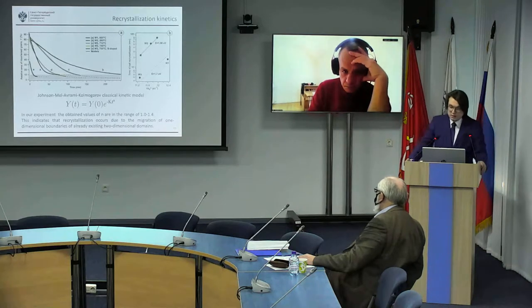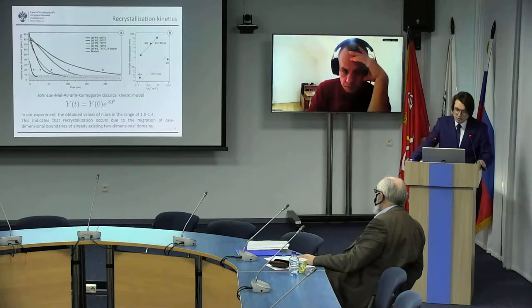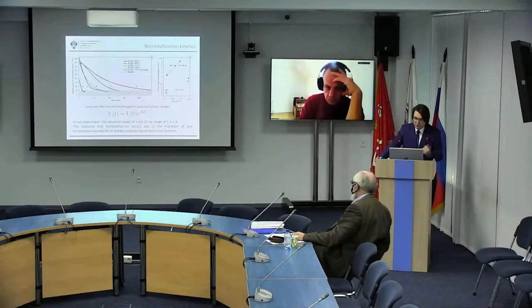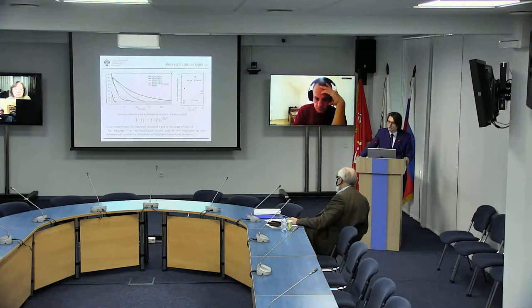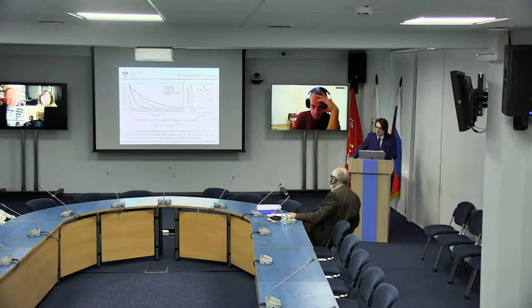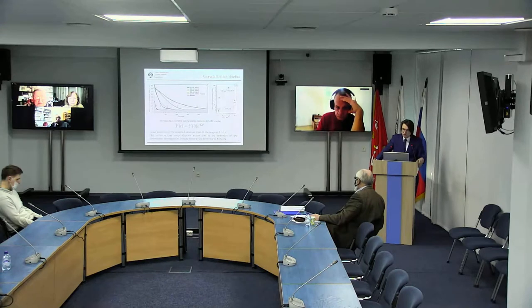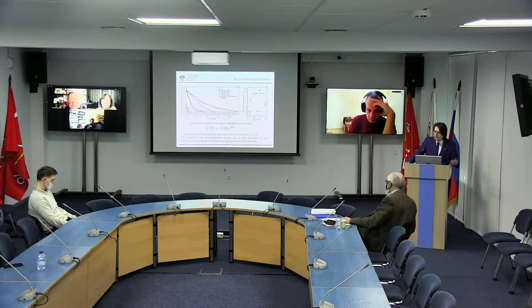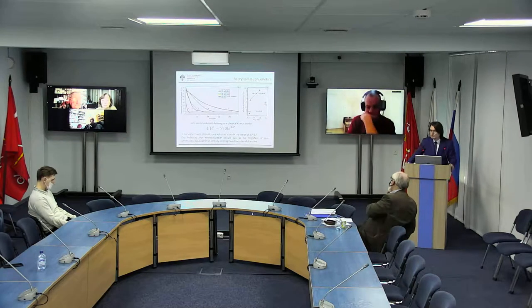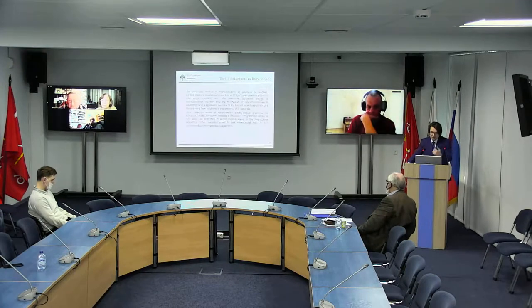Studying the kinetics was carried out using the classical Johnson-Mehl-Avrami-Kolmogorov model. And in this equation, we were interested in two values. First of all, the n parameter, responsible for the dimension of recrystallization. The values that we got demonstrate that recrystallization of graphene on cobalt happens due to the migration of one-dimensional boundaries of already existing two-dimensional domains. And the calculated activation energy of this process allowed us to provide the appropriate mechanism of this process.